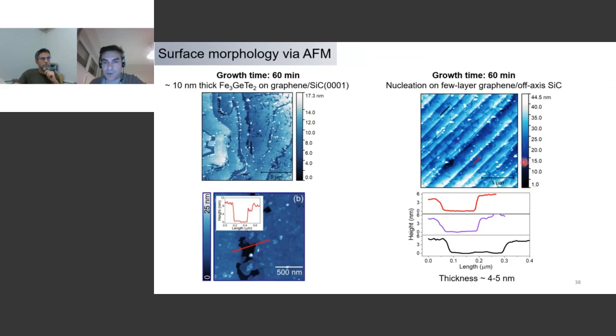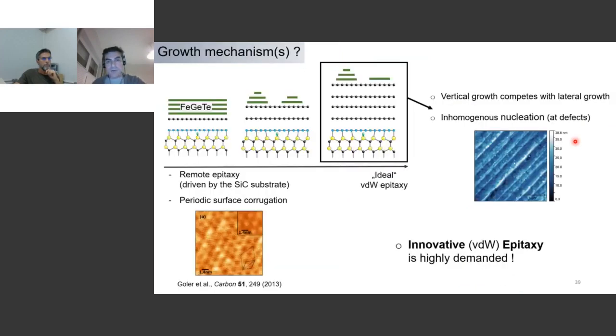And what we see is that for the same growth time, the growth is much, much slower. We get a thickness of about 4 to 5 nanometers, and it's not a continuous film. And why do I show that? Because now we come to the point, what is the growth mechanism happening here? And again, I show that because that's what we are interested in understanding.